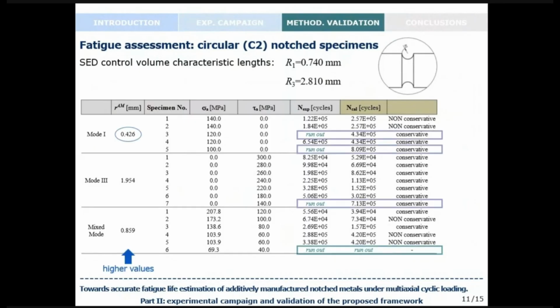campaign. Then, moving to the results related to the C2 notch specimens, also here you can see the values of the critical distance we compute for mode 1, 3, and mixed mode loadings. And as you can see, higher values are obtained in this case with respect to the V-notches case, especially for mode 1. We had 0.03 millimeters for V-notched, and we have here 0.4 millimeters for this case. And for the circular notch specimens, the methodology provides more conservative estimations, especially in the case of the runout tests.